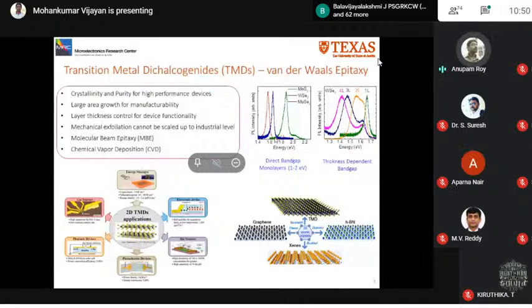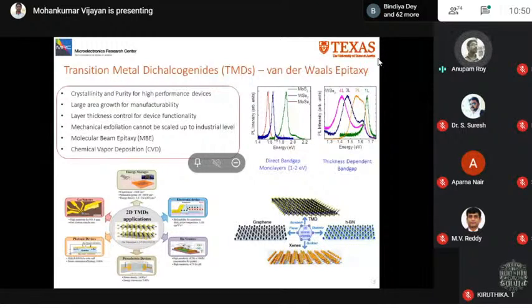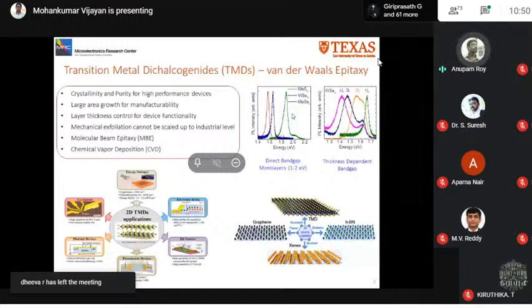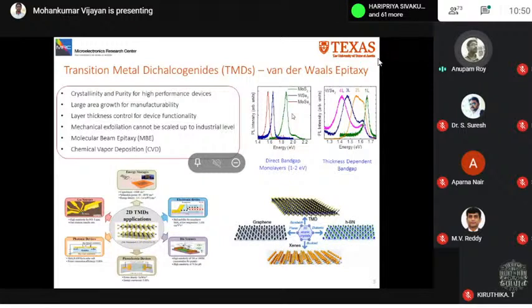Most of the 2D materials research is conducted on flakes exfoliated from bulk samples. But large area growth is very necessary for device application, and an optimized growth method is still required. We need highly crystalline and pure films for high performance devices. We need large area growth for manufacturability and layer thickness control for device functionality. To achieve all this, the two most reported growth methods are molecular beam epitaxy, MBE, and chemical vapor deposition, CVD. Of these two, CVD has so far been the most promising in growing large area TMDs with quality almost comparable to the exfoliated bulks.